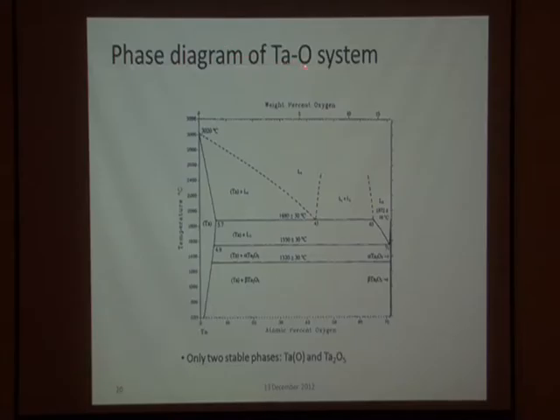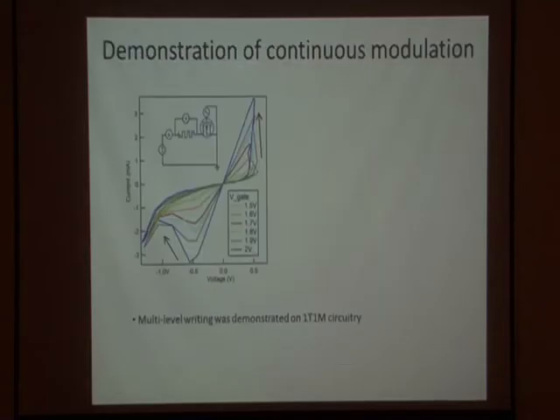Now the interesting thing about the tantalum oxide is that this is the phase diagram. And so there are only 2 stable phases. You have a little bit of oxygen diffused into tantalum, or you have the pentoxide. So that gives you a very good knob to turn. You can add oxygen atoms at will, pretty much. And for example, this is one way of doing that.